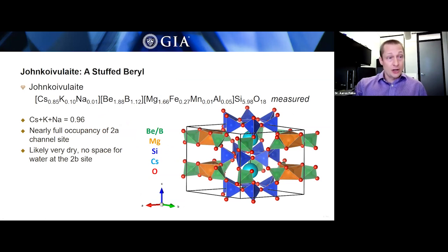One unique thing about johnkoivulaite among the beryl group minerals is that this site where the cesium sits, we call it a 2A site. It's a specific crystallographic site where the cesium likes to sit. Now, a lot of beryls actually have some alkali ions occupying these channel sites, these 2A sites. But in most cases, the amount of alkali ions occupying that site is less than 50%. So it's typically very low.